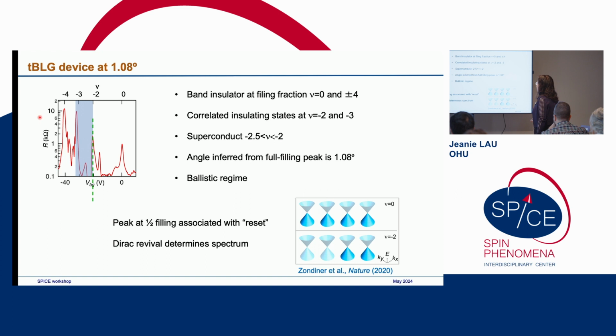The one at filling factor 4 is the band insulator, whereas the ones at filling factor 2 and 3 are the correlated insulating states. Superconductivity is observed roughly between 2 and 2.5 holes per unit superlattice cell. This is a device of very low resistance in the normal state, so we can estimate the mean free path is about the channel length, so we're in the ballistic regime.